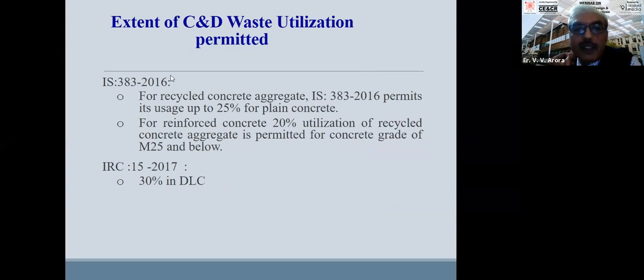In 383 2016, recycled aggregates are permitted up to 25% for plain concrete, and 20% for M25 and below. And for PCC, 25%. And in IRC 15 2017, 30% has now been permitted in the DLC layer only, but the upper layer, the pavement quality concrete, it is not yet permitted because the abrasion issue is there. But if we use a two-lift construction, that document is coming, there we will be able to use the C&D waste aggregates in the lower part of the PQC.